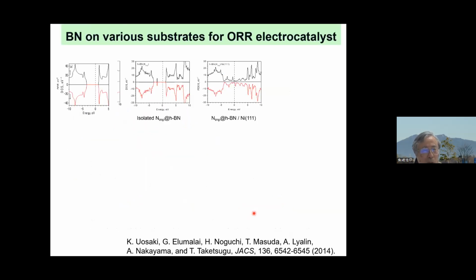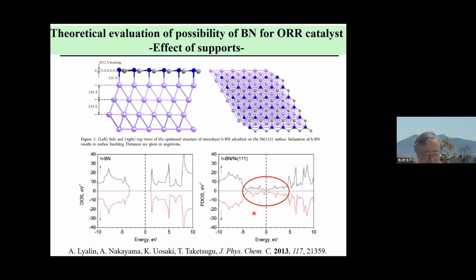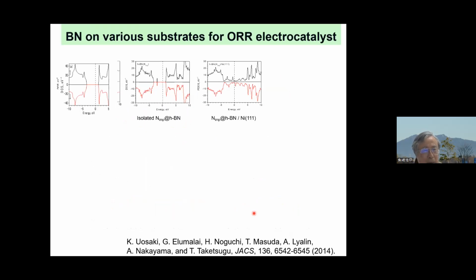And furthermore, we carried out free energy calculation for oxygen reduction. But nickel is not a good substrate for experimental oxygen reduction reactions because nickel can be oxidized or become a hydroxide in alkaline solution or dissolve in acidic solution. So we used gold 111. Of course, gold is still a precious metal, but as a proof of concept study, it may be nice.